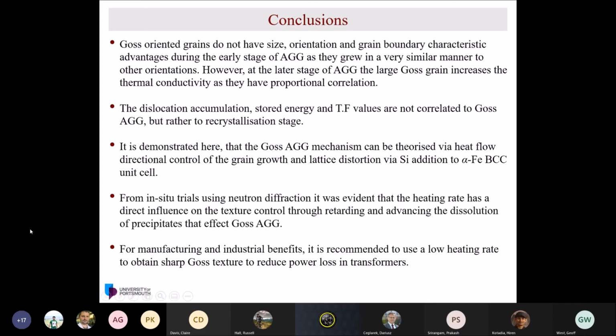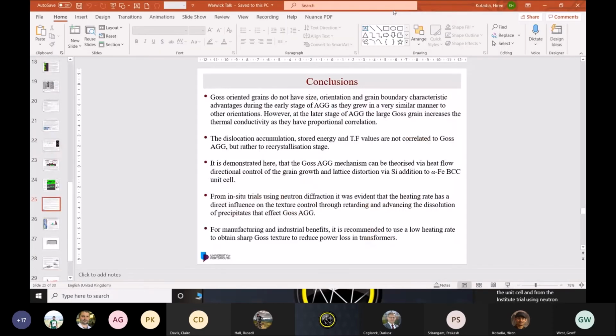And it's also demonstrated that the Goss abnormal grain growth can be theorized, as we discussed now, with the distortion of the cubic high symmetry by adding silicon and also the heat flux direction to promote the Goss abnormal grain growth in the unit cell. And from the in situ trial using neutron diffraction, it was evident that the heating rate has a direct influence on the texture control through retarding and advancing the dissolution of precipitates. And for industrial benefit, we recommend using a low heating rate during secondary annealing to obtain a very sharp Goss texture to use for transformers.